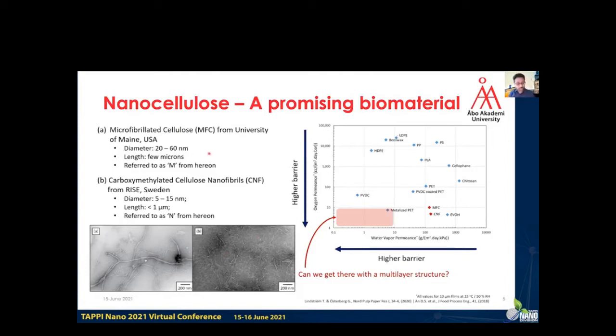Without going too much into the details, I would just explain the different kinds of nanocelluloses that we used in this work, which are two types. One is a microfibrillated cellulose from University of Maine. This is purely mechanically produced, with diameters between 20 to 60 nanometers. And then we have a second type, which is carboxymethylated cellulose nanofibrils produced at RISE, Sweden, with diameters between 5 to 15 nanometers. Both of these are nanoscaled fibers, and we just used microfibrillated to distinguish the coarser one from the finer one. And we have a TEM image to show the fiber structure here at the bottom.